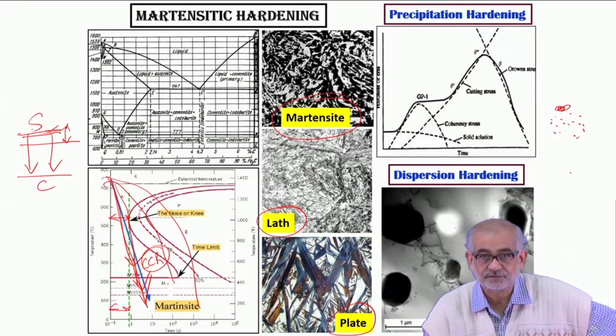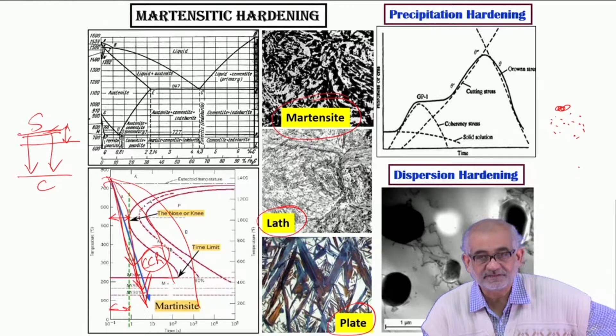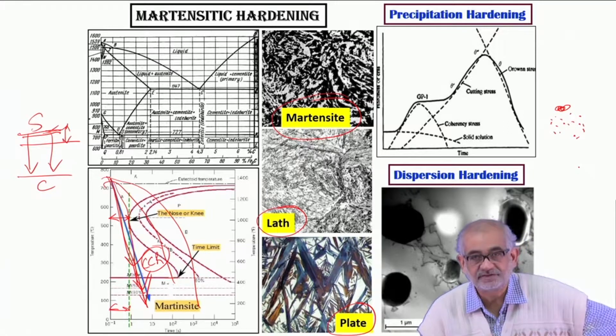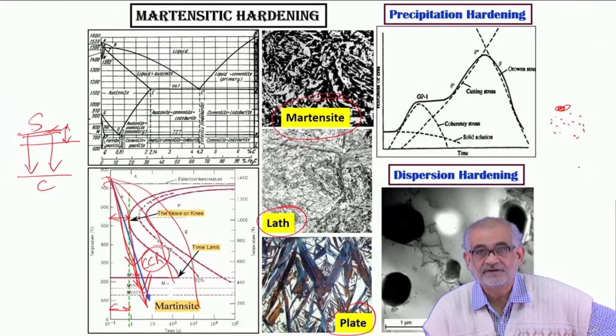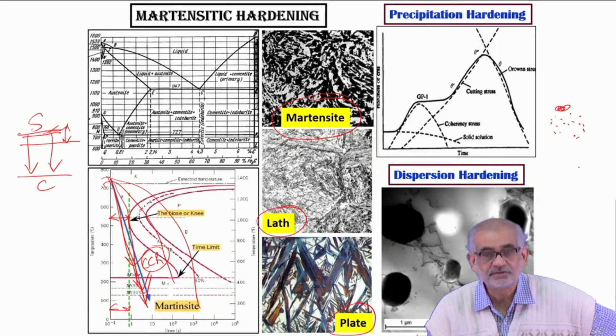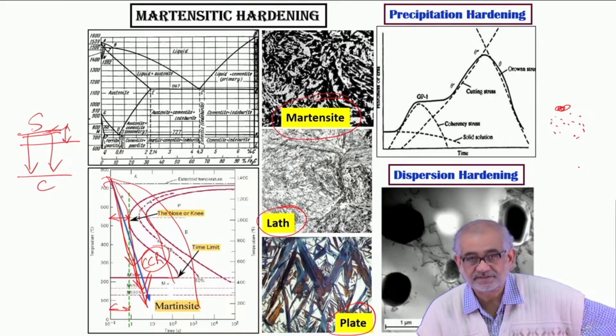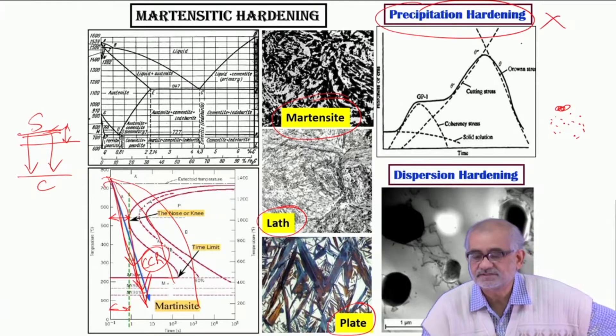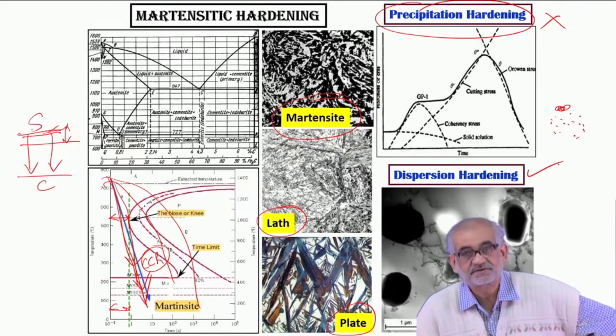At the same time the surface will be at least semi-coherent if not coherent, but coherence is not quite expected in the case of nitride because the crystal structures are very different from ferrite. So if you have two phases alpha and beta with vastly different crystal structures, you do not expect coherency at the matrix. If you do not have coherency then obviously you do not expect precipitation hardening, but you certainly expect dispersion hardening.